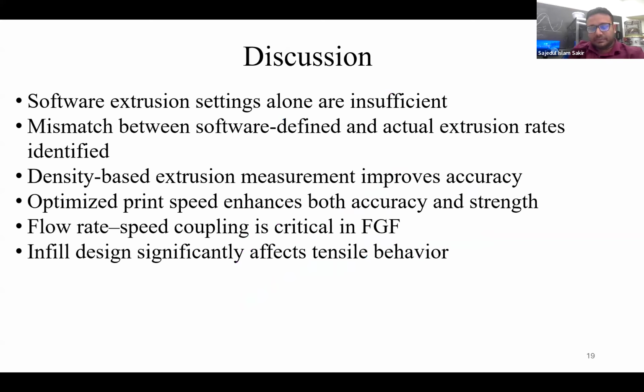And from this presentation, the discussion part is that software extrusion settings are insufficient. We have measured the experimental flow rate and software extrusion flow rate. It's almost 90% to 95% range. Although there were some mismatches, when I first started, there was so much difference, like 50%. From the experiment I got some 50% result, but now after modifying the settings and everything, it's showing 80% to 90%. But when I started, I faced lots of difficulties, and there was so much mismatch between the software defined and actual extrusion flow rates.